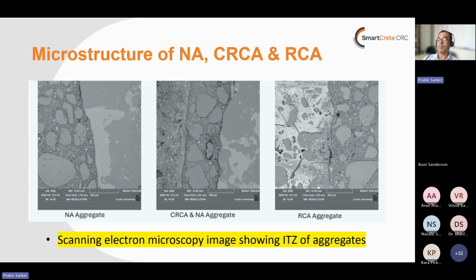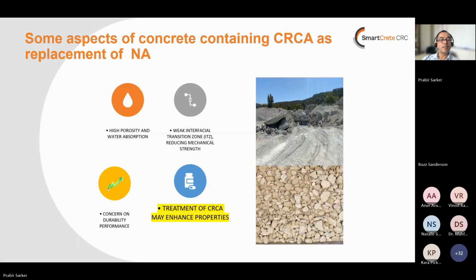So that contributes to some of the properties of concrete that we see. The decline in some of the properties, whether using CRCA or RCA, is due to the effect on the ITZ. Okay, so from this we can summarize that yes, there is a compromise of some of the properties by using either CRCA or recycled C&D waste aggregate. So there is room for improvement.